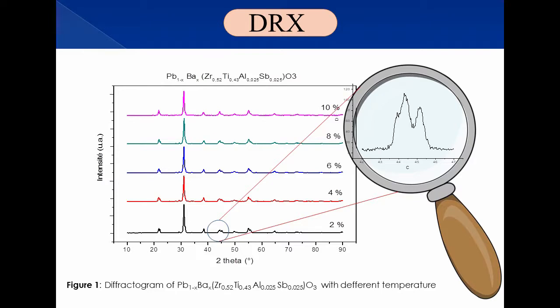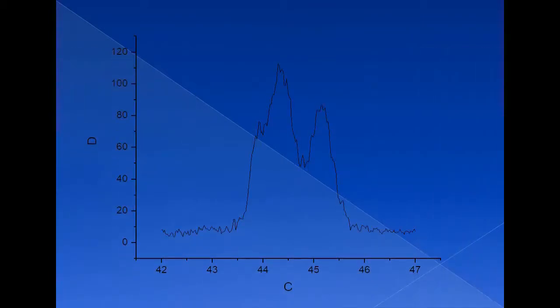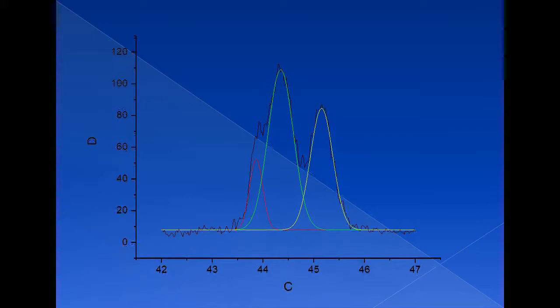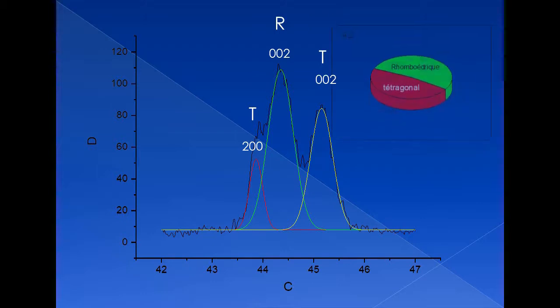For more explanation, this is our diffractogram. Actually, there are 3 peaks like we see here. The first and the third peaks are the tetragonal phase, and the second is the rhombohedral phase. So we can calculate the percentage of existence of these phases. We can see that the rhombohedral phase is 52% and the tetragonal is 47%.